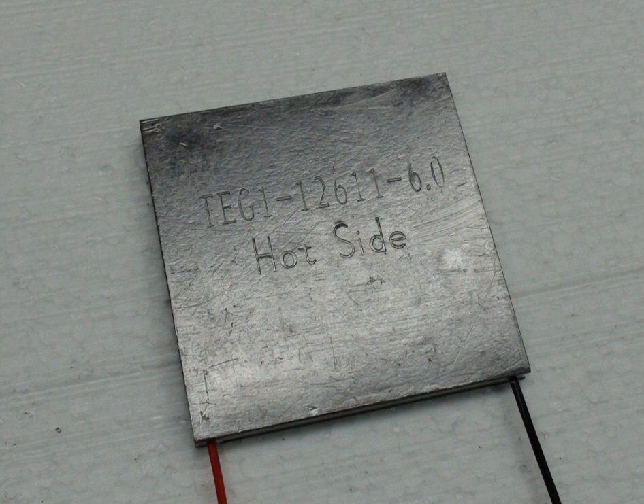In order to increase the figure of merit ZT, a material's thermal conductivity should be minimized while its electrical conductivity and Seebeck coefficient are maximized. In most cases, methods to increase or decrease one property result in the same effect on other properties due to their interdependence. A novel processing technique exploits the scattering of different phonon frequencies to selectively reduce lattice thermal conductivity without the typical negative effects on electrical conductivity from the simultaneous increased scattering of electrons.